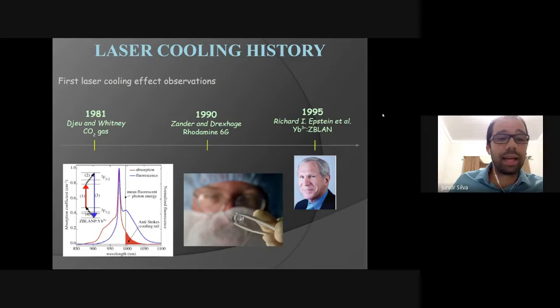And this system will try to get the equilibrium again, and will absorb phonons from the lattice of the material. And these phonons go out of the material through luminescence. And after it goes down here to the ground state, it absorbs phonons again. And this cycle cools the material, okay? And this is how solid state cooling works.